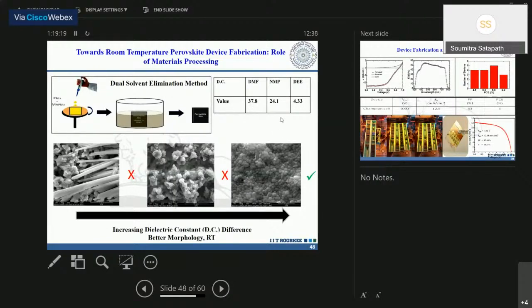Now, what is the reason behind that? The difference in the dielectric constants means a difference in the polarity, and the solvent boiling point is also different. When you choose a solvent which has almost the same dielectric constant, you do not get a good quality film. When you choose the opposite dielectric constant, you get a good quality film. What is the reason? Then we played around with a number of solvents, like 60 to 80 different kinds of solvent, all solvents available and where it is soluble.